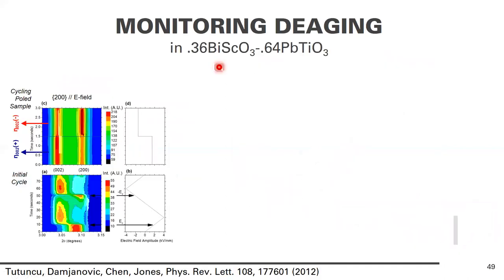And so we took a material, bismuth scandate lead titanate, and we first poled it as shown down here. So you can see characteristic intensity changes associated with poling. And then in the poled state, we applied a cyclic electric field. And so here's the positive state of the electric field. Here's the negative state of the electric field. And through the equations that we showed earlier, you can calculate eta 002 in the positive and